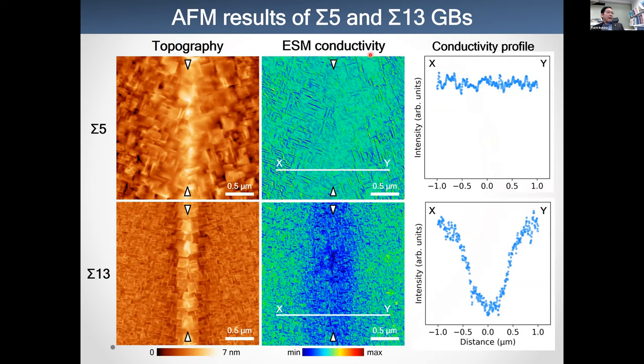Well, this is the topography of sigma 5 and sigma 13 grain boundaries. And this is the ESM conductivity. And these are the ESM conductivity profiles across the XY direction like that. As you can see, at the sigma 5 boundary, the conductivity of the grain boundary is almost similar to the grain interior. But the conductivity at the sigma 13 grain boundary is decreased compared with the grain interior.